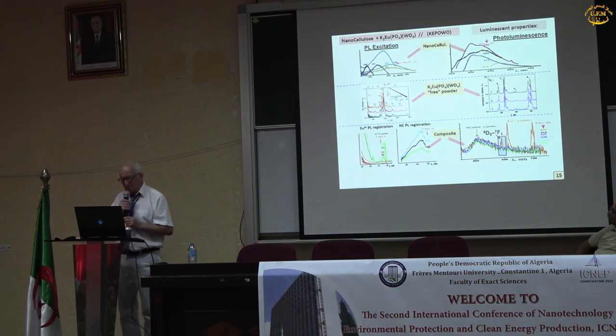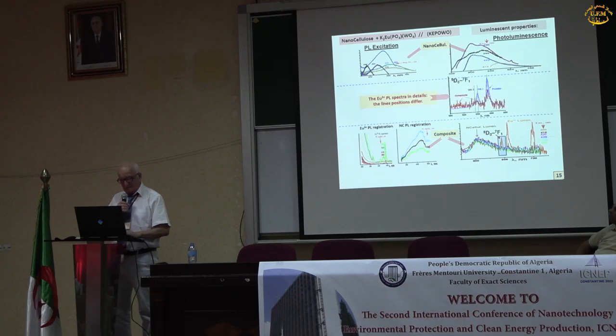And concerning luminescence properties, we see the spectra in the left column, the photoluminescence excitation for nanocellulose, and the photoluminescence spectra at the right for nanocellulose. In the middle you see the spectra of photoluminescence excitation and luminescence of the powder, only of the powder. And at the bottom you see the spectra of the composite. We see that the photoluminescence spectra of europium 3+ ions, active in luminescence, differ for the powder and for the composites.